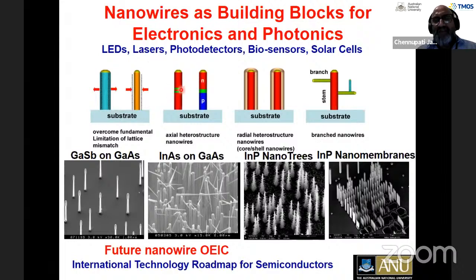You can also create heterostructures within the nanowire. For example, this green material is different than the red material. That means you can create quantum wells or quantum disks and so on. You can also create PN junctions within the nanowire. That means you can make single nanowire based lasers and LEDs and solar cells, photodetectors and other things which I will come back to. You can also create radial heterostructures, core-shell nanowires. This red material is different than the pink material, so you can create multi-layer structures also. You can also create branched nanowires, which allows us to make three-dimensional architectures.